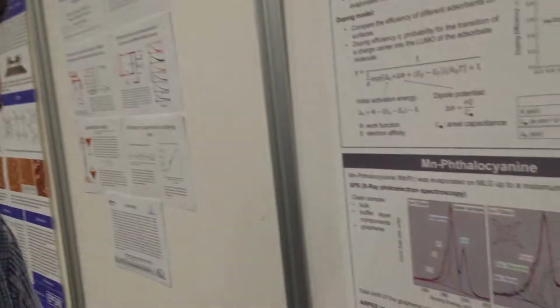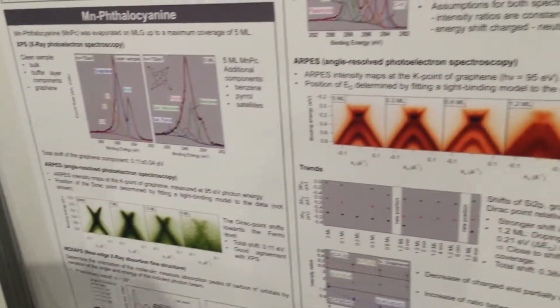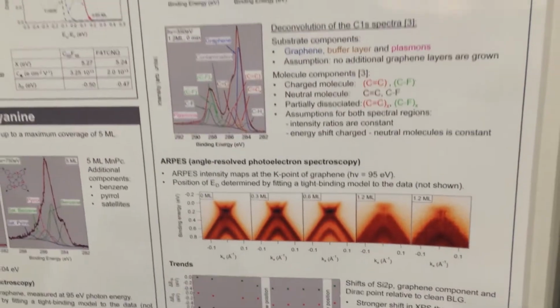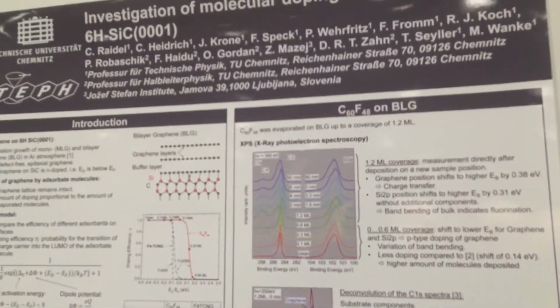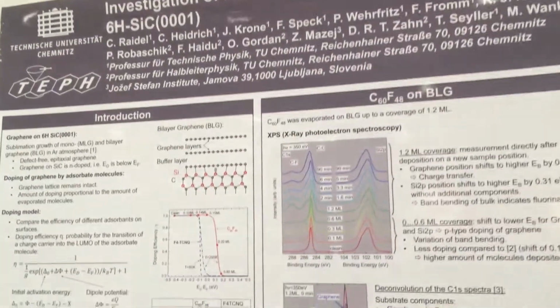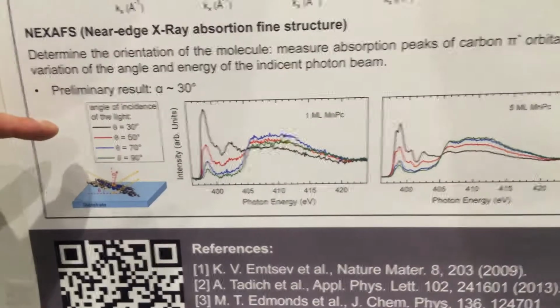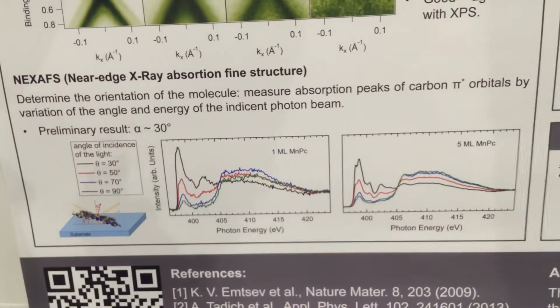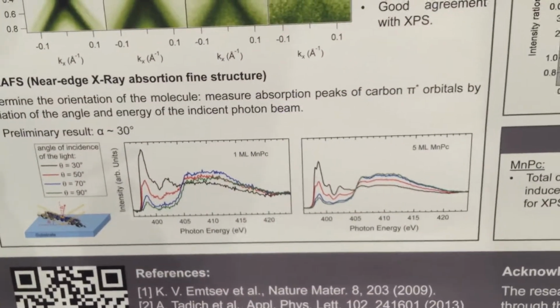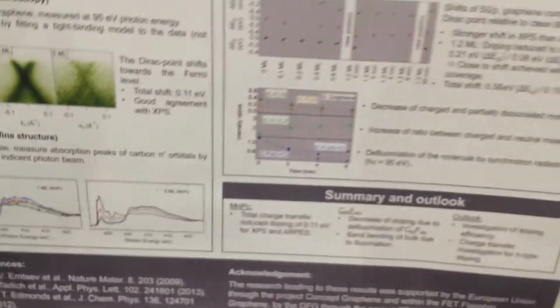You can also see from NEXAFS, this is mainly calculated by a colleague of ours, that this molecule stands up. The preliminary result will be that it's standing 30 degrees up from the sample surface. Let's come to the other molecule we investigated.